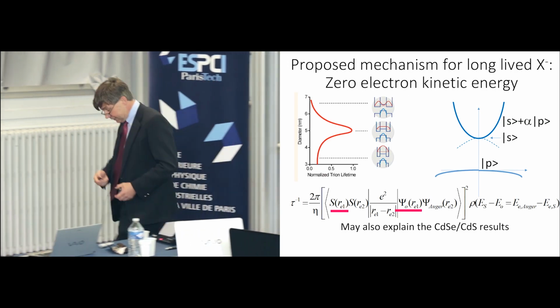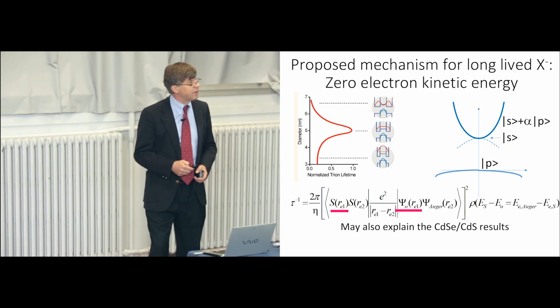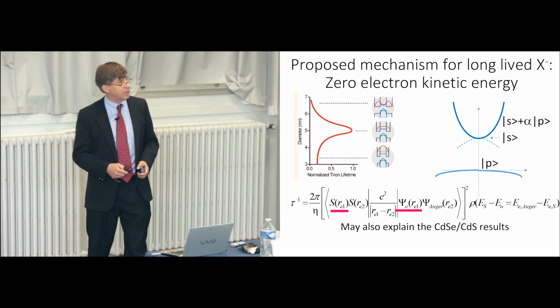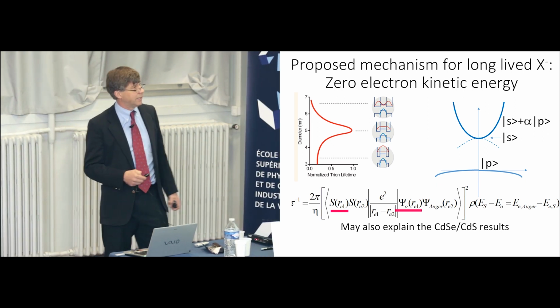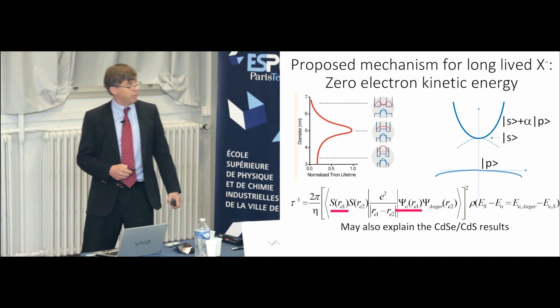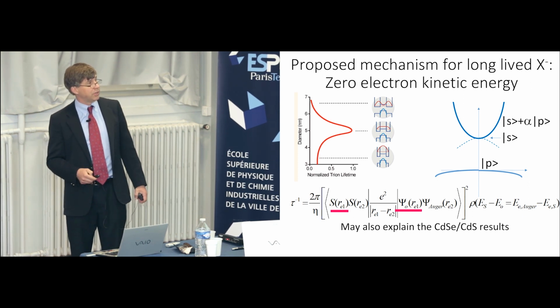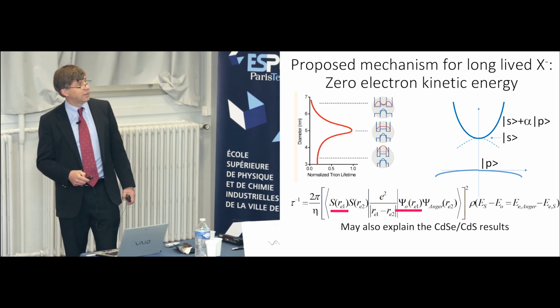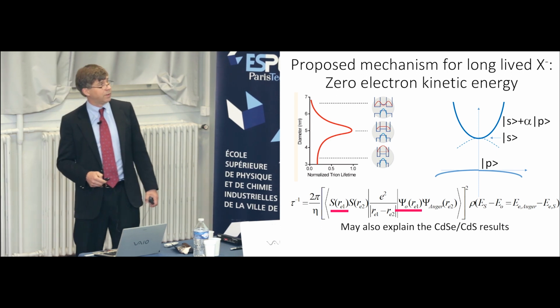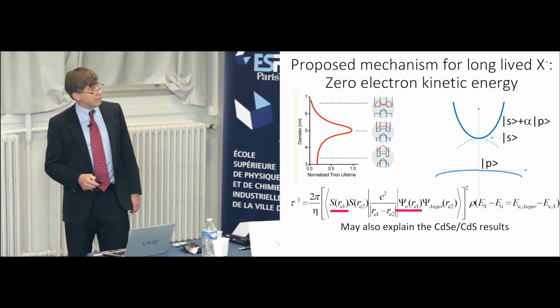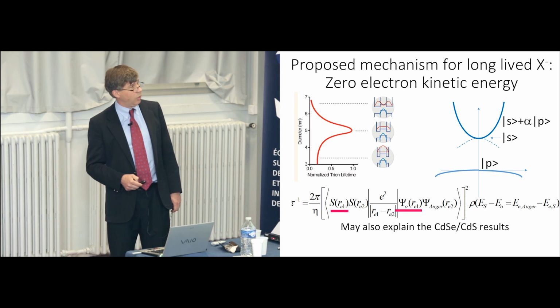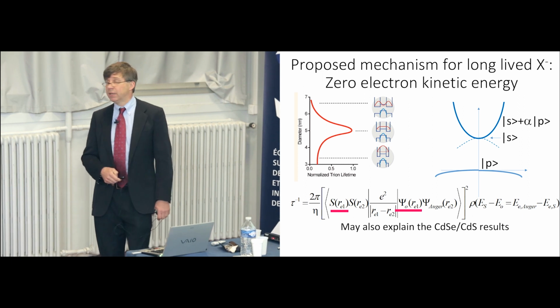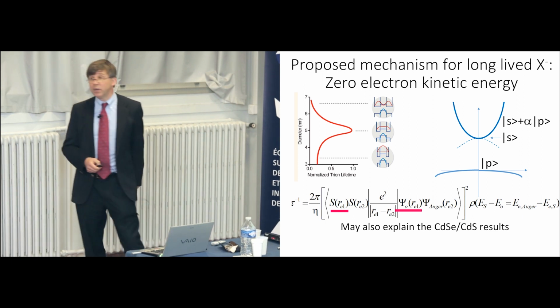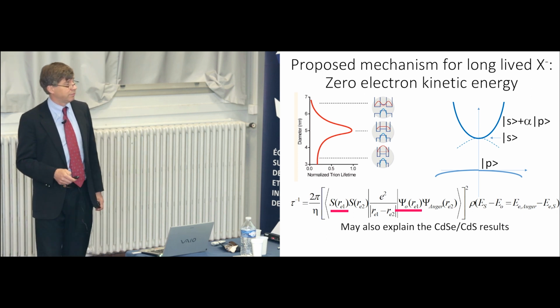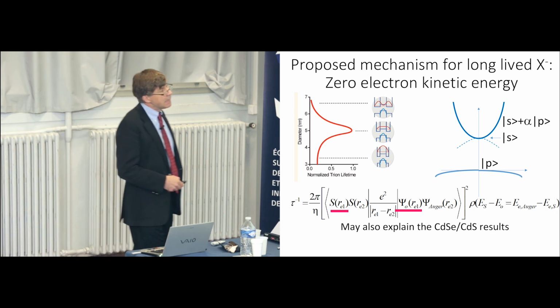We looked for a slightly less qualitative explanation, and then we ended up looking into this matrix element that Sasha has told us to look at, which is the Auger relaxation process, where we've got this Coulomb interaction between the electron states, the two electrons, and then the hole. And what you find is that it's really the overlap of the hole wave function and the electron wave function that matters. The electron, the particle has to be at the same position in this matrix element.